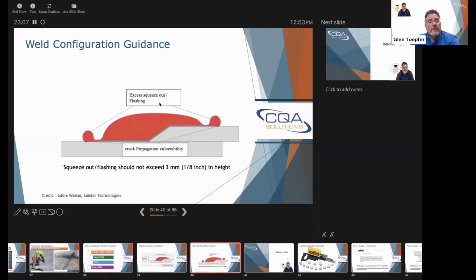And your weld configuration, you can see here, Eddie's diagram has the squeeze out, and you can see that studies have shown that with excess squeeze out, you get more heat there, you get crack propagation vulnerability, and that can cause stress cracking in the future. So you want them to be uniform, but the recommendation is that they should be 1/8 inch in height or less.